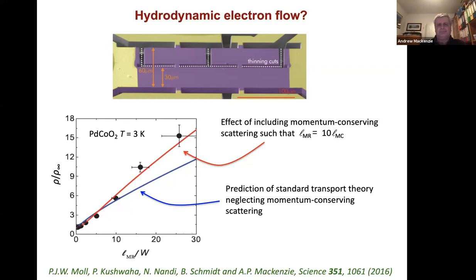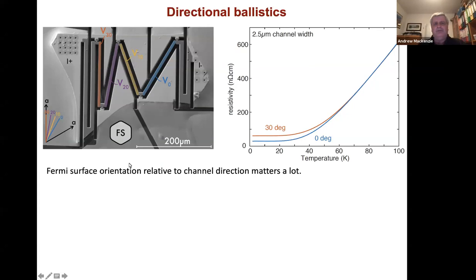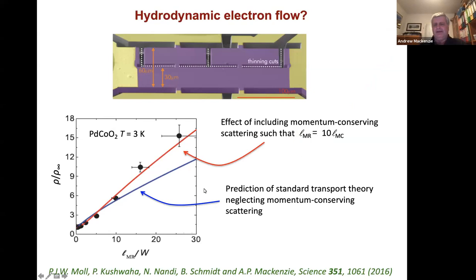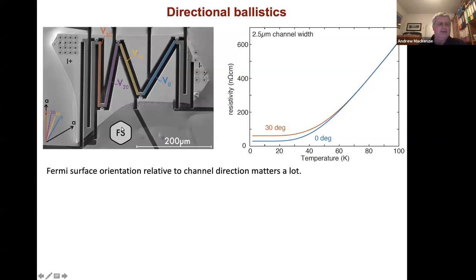The story isn't that simple, but for quite an interesting reason. When I told you that we did a standard transport theory there, we did what was available at the time, which was including ballistic transport, but ballistic transport assuming a circular Fermi surface of the kind that would exist in, say, a doped semiconductor. Actually, we wondered at the time whether the hexagonality of our Fermi surface was going to be a significant factor.